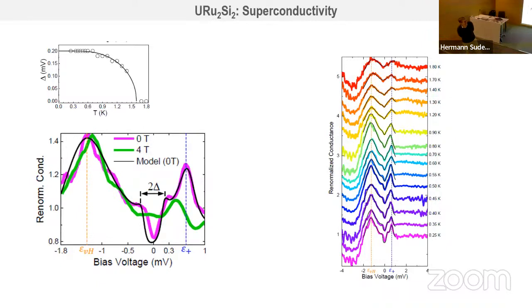So this material is non-centrosymmetric. No, it is centrosymmetric. And it's four-fold in the surface. Actually, structurally, there is nothing that explains that, really. Unless it's a reconstruction that froze, and then you should see in some regions perhaps one orientation, and in other regions another orientation. Which you don't. No, we always observe the uranium. I mean, we can observe the uranium, the ruthenium, and the silicon lattice. The ones which are easiest to observe are the uranium lattice and the silicon lattice. We have mostly spent time on the uranium lattice, which we thought was more interesting. And we never see anything which could tell us that there is a symmetry broken there.